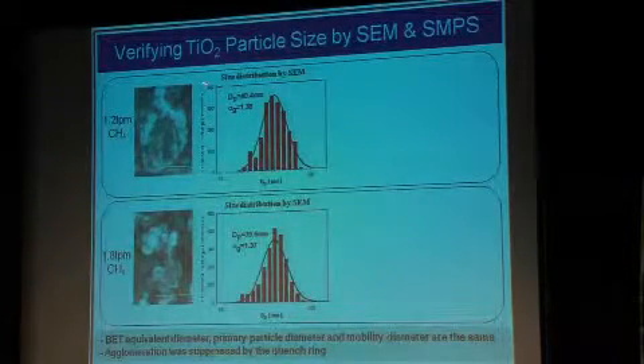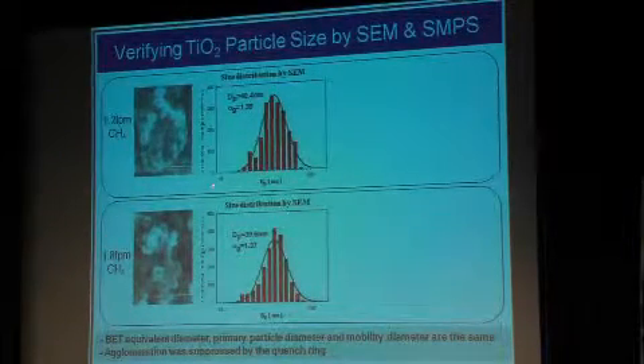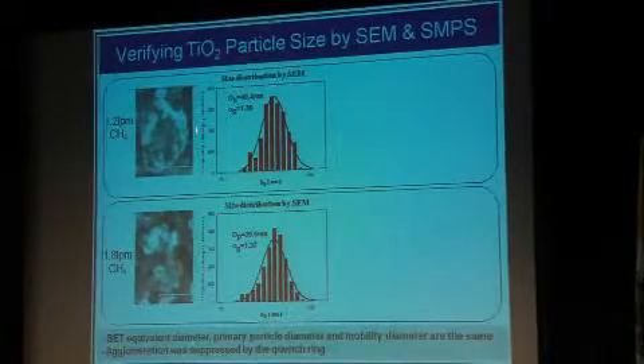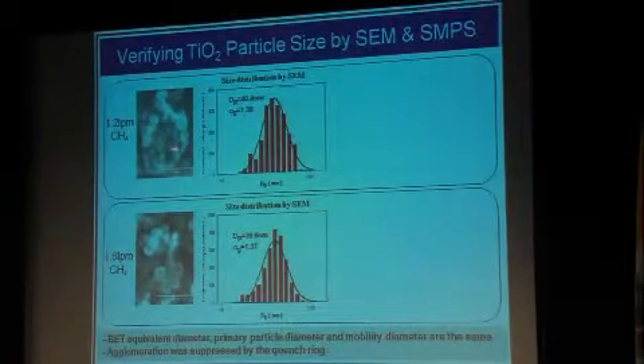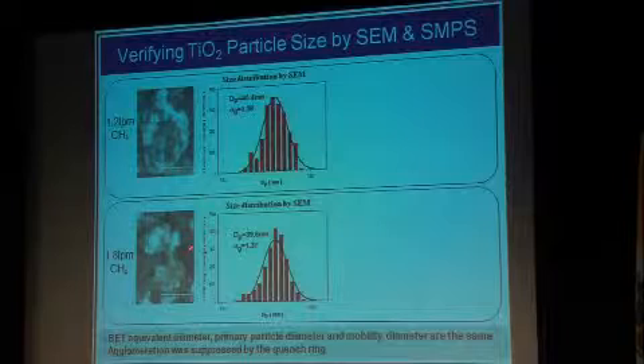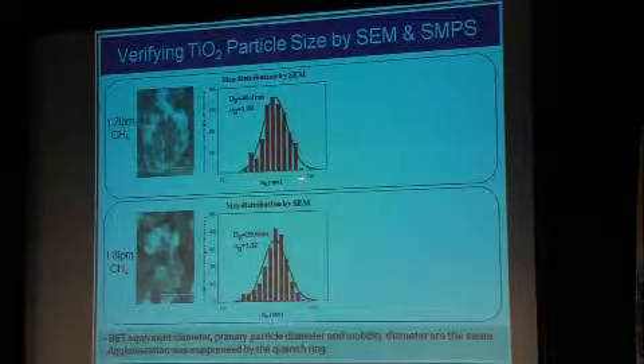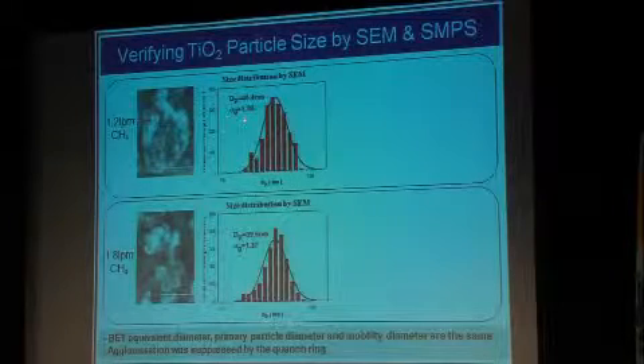I could also obtain different particle sizes, and this is again particles that are collected. These are loose agglomerates. They're just piled onto the filter, and you can see there's a distribution. The geometric distribution is about 1.4, 1.38, and so forth.